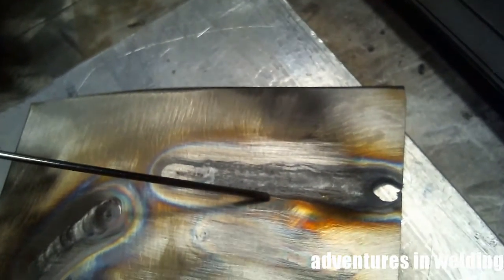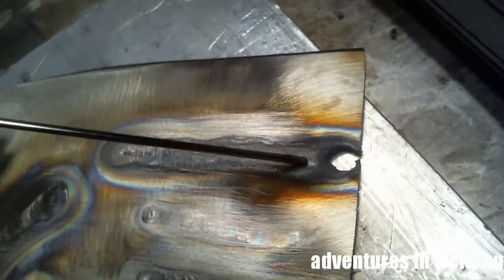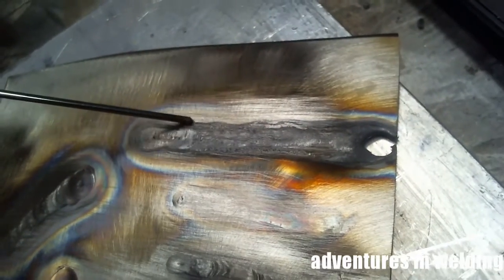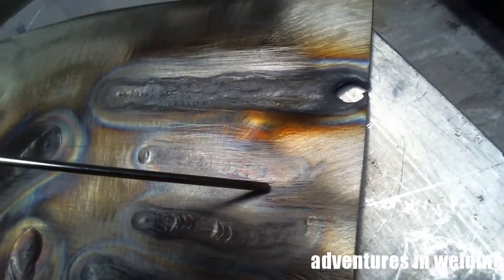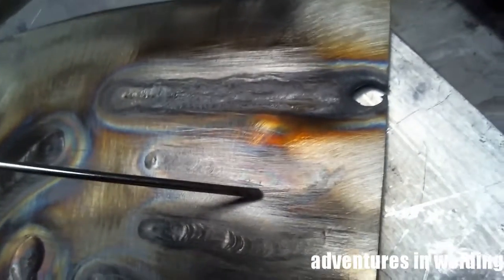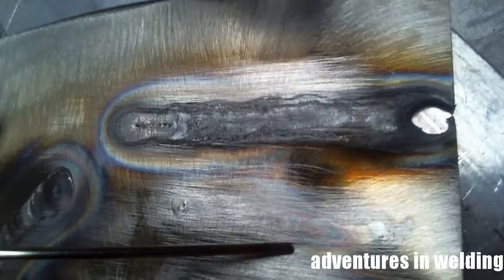Alright, there's our first weld. We tried at 50 amps. And as you can see, that's a little too hot for that. Down to, what was it, about 30? I mean, you can barely see the weld in there. Up to 40, a little bit better. Getting here about 48.